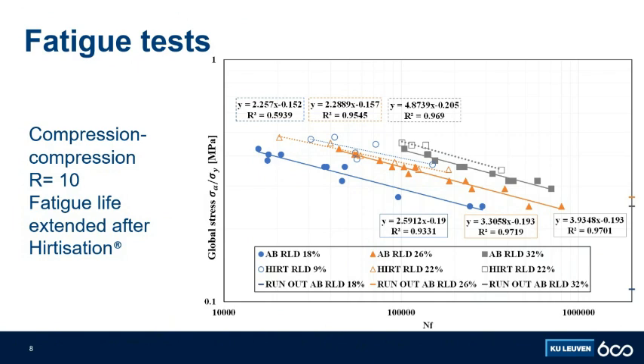For the fatigue tests, I have applied a compressive load, compression-compression ratio equal to 10. And I have also observed a fatigue life extension. And here's the explanation. On the y-axis, I have the amplitude stress divided by the yield stress of each category for the sake of normalization. On the x-axis, we can observe the lifetime in cycles. The solid markers are the as-built, and the hollow markers are the Hirtisation treated.